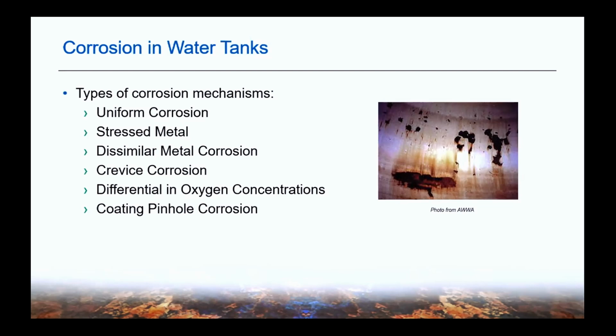Another thing that we see in water tanks is that steel that's under stress can be anodic to unstressed steel. Some of these stresses can be caused by welding or through the bending or forming process. In my time in the field, a very common form of corrosion that I've personally observed is dissimilar metal corrosion. Putting on your NACE hat and talking about the galvanic series and different metals, you know that different metals in contact with each other will establish a corrosion cell, which will see corrosion occur at the more active metal. You may see this in a tank at weld seams, with fasteners, and with any other attachments.